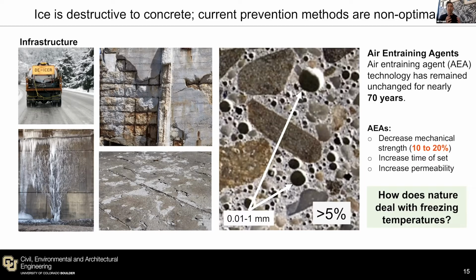So in places where you're also experiencing freezing and thawing, you're probably also worried about ice forming on the roads, so you're salting the roads. And these tiny little air bubbles act as super highways for those salts to come into the concrete and cause other damage, like chloride-induced corrosion within the concrete. So good solution, but it has some consequences.